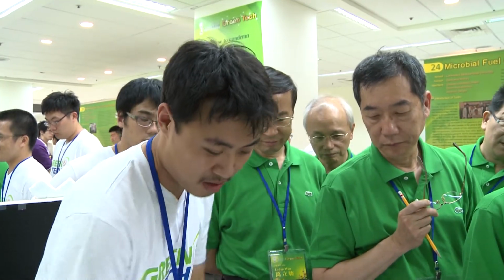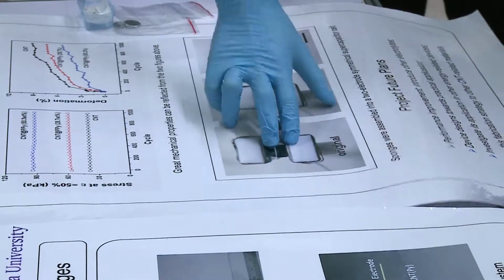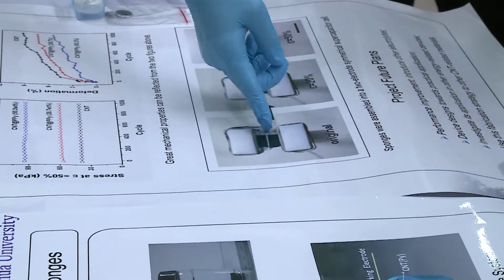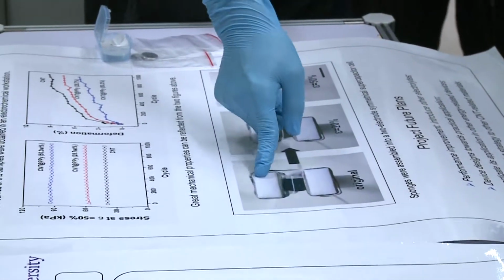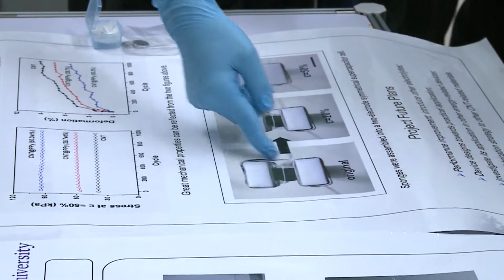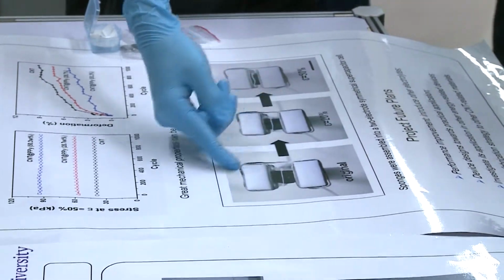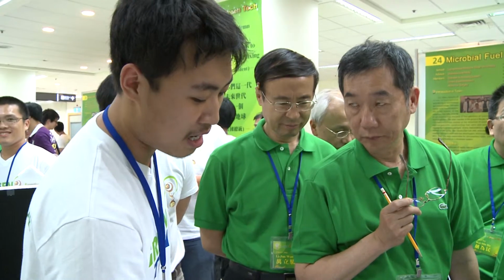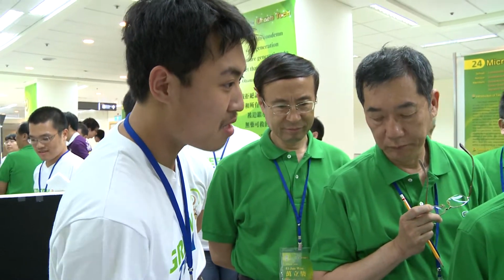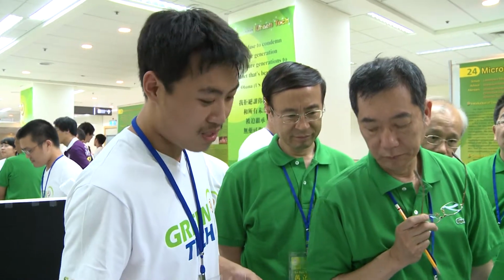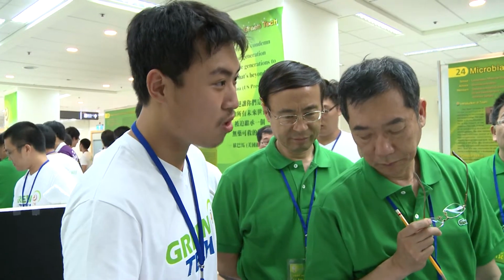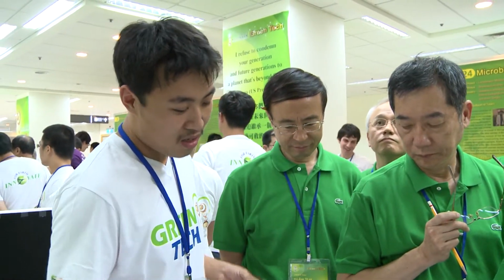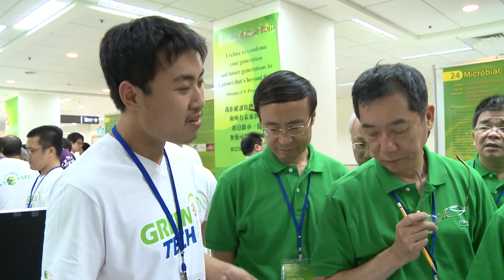And this is the measurement process. We put two sponges here, with filter paper beside them, between two slabs. And we put platinum wire around the box here, which acts as a collector. This method was made by ourselves, and it's quite convenient and easy to control, because our budget is very limited.